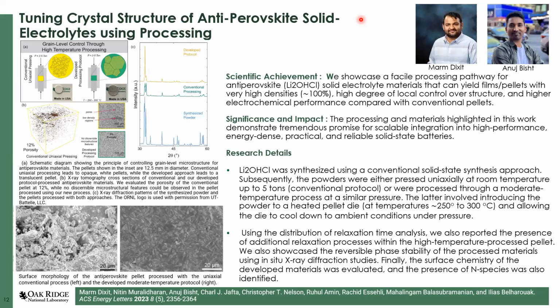We also do processing. So you can take a standard material, and by means of different processing methods, try to improve the properties of this material. In this case, this work is on a solid state electrolyte, which was spearheaded by Marm. What he showed is that by a very straightforward process, using very moderate temperatures and pressure, you can stabilize this antiperovskite electrolyte in the cubic phase, which has very good electrochemical properties.